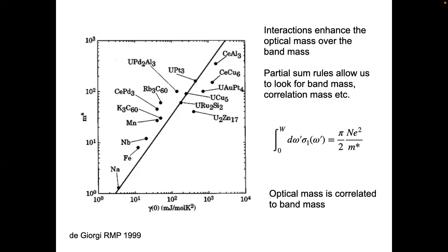What about the non-Fermi liquid where gamma is divergent? Do you have mass involved? So it would be interesting. It's hard, though. It's divergent in some non-Fermi liquid, perhaps logarithmically, and it's hard to see logarithmic divergences. So I think that's one important consideration. There has been no evidence for logarithmic divergences in an optical response for an effective mass.